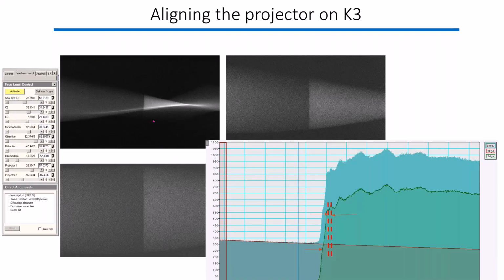So these are examples of the imaging or the 2D spectrum you've seen, and from the camera, this is how it behaves if you manually align the system. You are opening this, and you can see the spectrum opening so that you can have an even, or close to even, illumination. If you have good eyes, you can probably see the edge in focus. You can probably see a few ripples there already, because these are very short acquisitions, a couple of seconds.